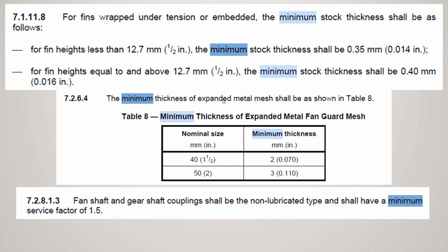And now coming to the fin thickness, the thicknesses provided are the stock thickness, but after finning, the tip thickness will be different because of the thinning effect during the spiral finning. But anyway, we will just come to stock thickness: for fin heights less than half inch or 12.7 mm, the minimum thickness is 0.35, and for 12.7 mm and above, the stock thickness shall be 0.4 mm.